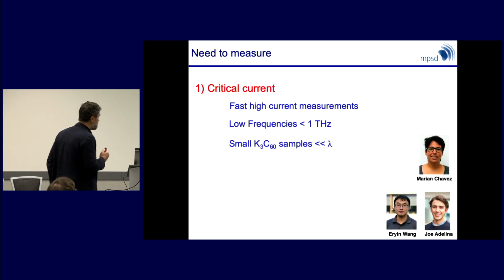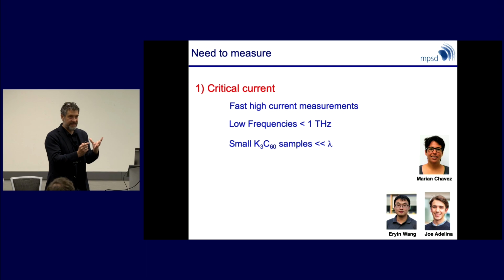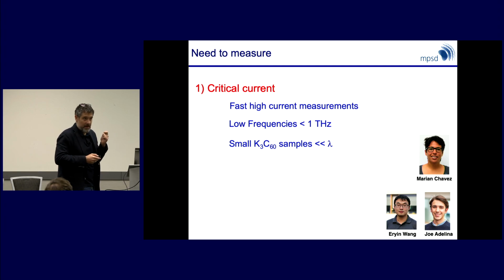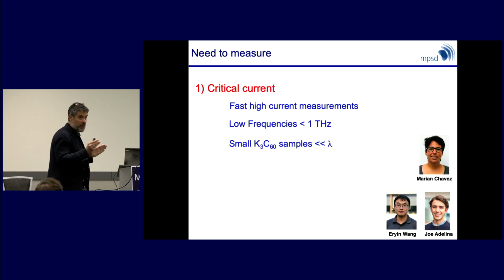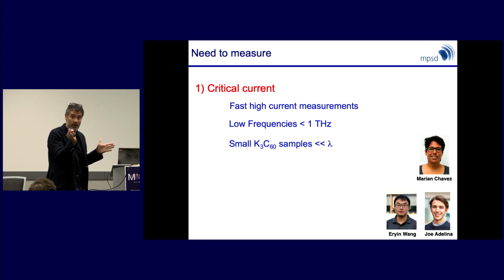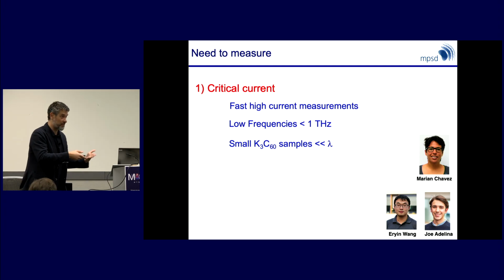So what you need to do is generate this state, which lives, let's say, a nanosecond. And now what you're going to need is a fast current. You need this current to be at low enough frequencies, far below a terahertz, where you don't have excitations of the system, to expose the critical current response.